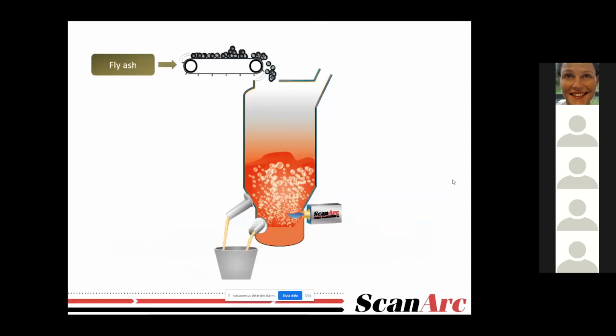So going back to the overview of the process, what about the fly ash then? Well, it goes in at the top here and it falls down to the molten bath. We don't use only fly ash because it has most often a very high content of lime, and we would like to have the ratio between lime and silica with more silica than what is usually the content in the fly ash. Because if you want to create this glassy fraction of the solidified material, we need a little bit more silica, and also we want to have a better flowing slag. It's called less viscous or more viscous.